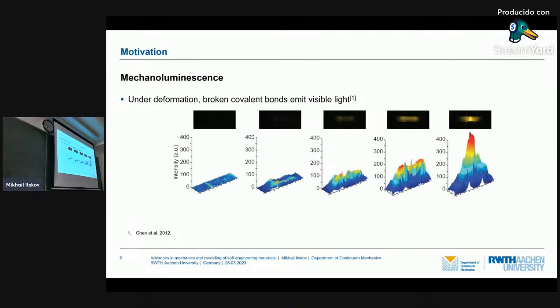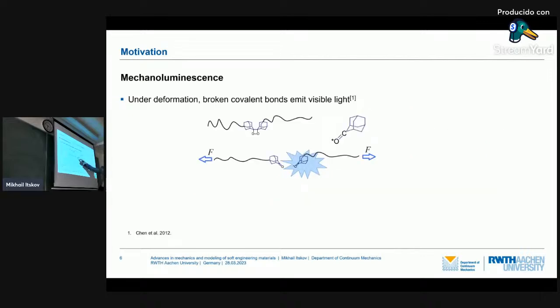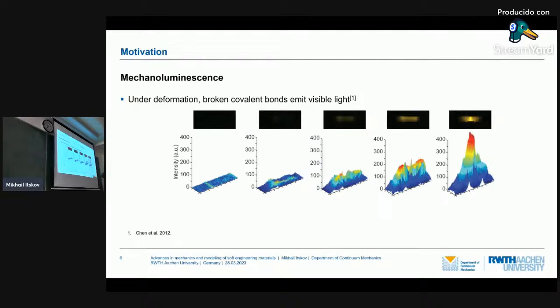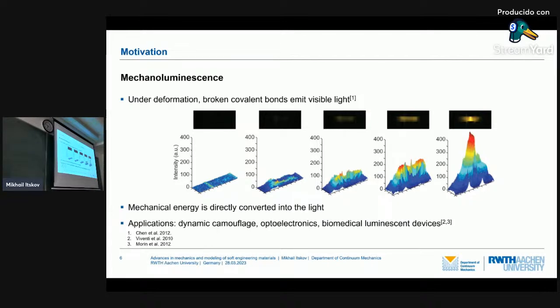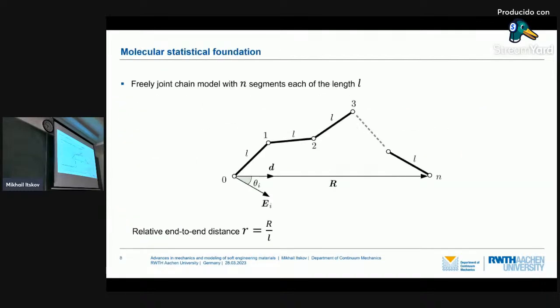Another important effect: if you add so-called dioxetane molecules to rubber, under loading these molecules break, and this breakage emits visible light. You see here this piece of rubber which, under loading, begins to emit light, and this is also a very interesting effect. This way we can see how much damage is inside the rubber. Rubber parts are usually very cheap, O-rings for example, but if one breaks inside of a motor or something else, the damage can be huge and very expensive. So this is the application of this effect. There are many applications already in dynamics, some of them optoelectronic, biomedical, luminescence devices, and so on. So this is what we are going to discuss in this context.